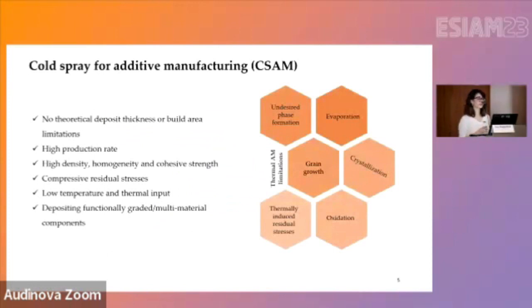Why are we pushing cold spray for additive manufacturing? Cold spray, as I mentioned, has been established as a coating deposition technique, but there are a set of parameters that would promote its application for additive manufacturing. First of all, there's no theoretical limit for the thickness of the deposit that we can have. We can start from a few hundreds of micrometers to a couple of centimeters. We can get very high production rate, much higher compared to other additive manufacturing techniques. In comparison, let's say with laser powder bed fusion, we can get 20 times higher deposition rate. Much higher density, very homogeneous structure, and high cohesive strength.